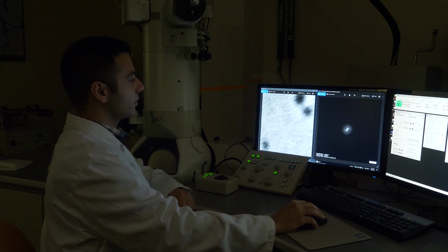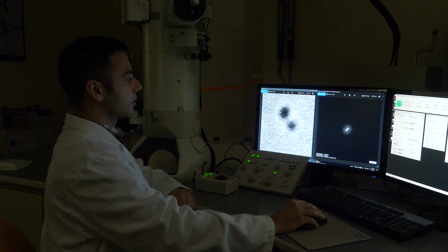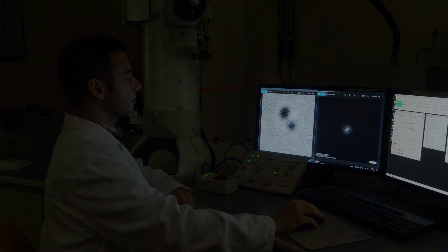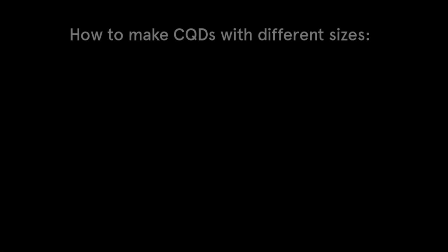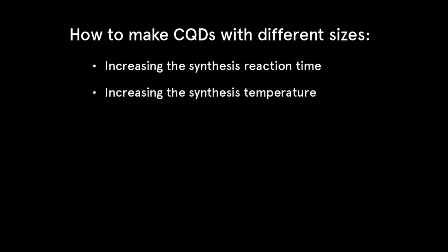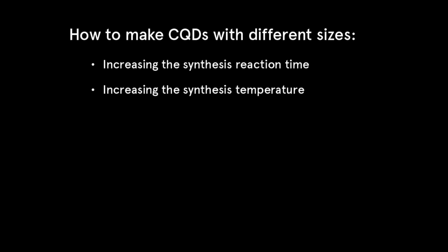You might be wondering if there is a chance to change the particle size of the carbon quantum dots. I should say yes, it is possible. We can change the synthesis parameters to achieve particles with different sizes. For example, to achieve particles with bigger size, we can increase the reaction time and the temperature of the furnace during the synthesis of the carbon quantum dots.